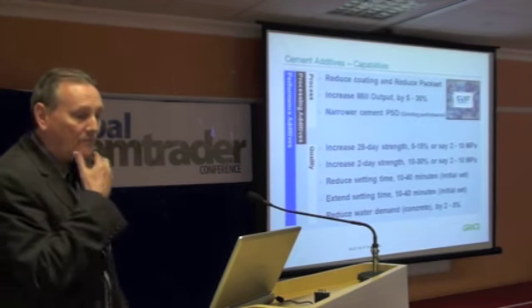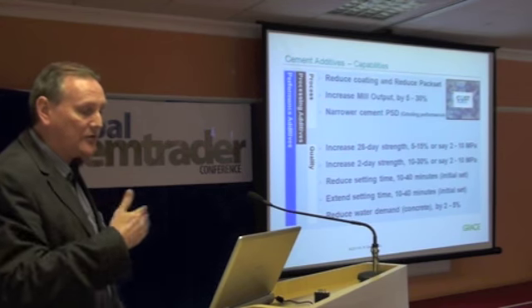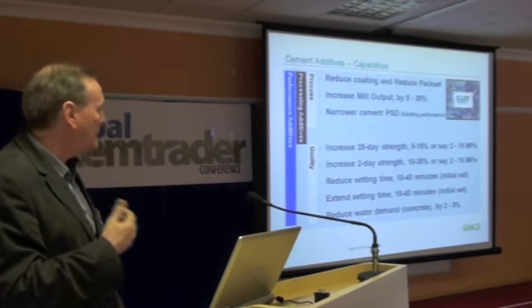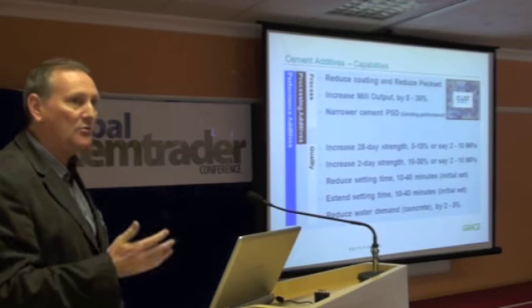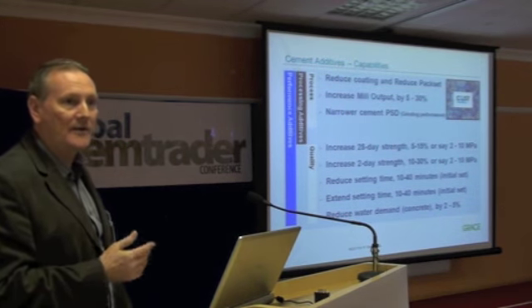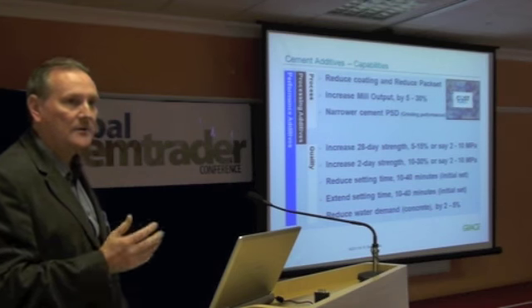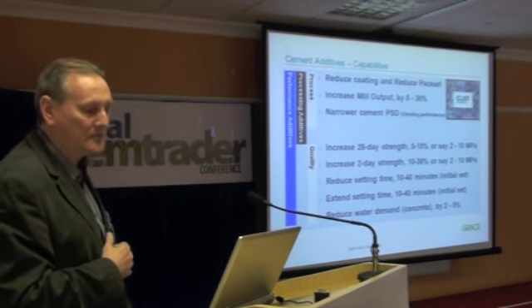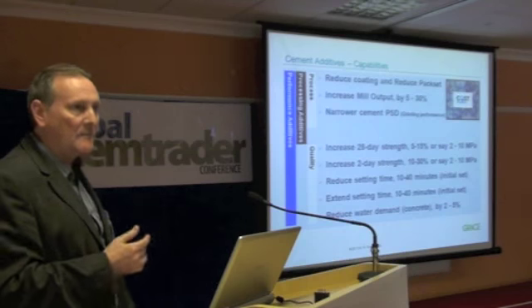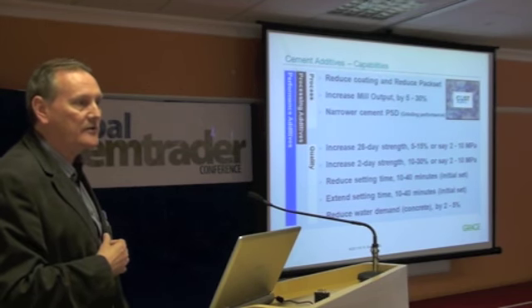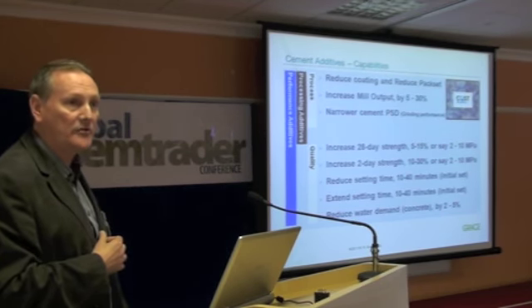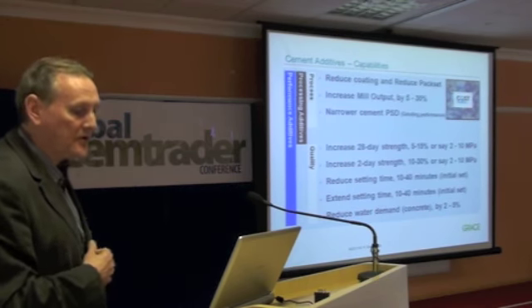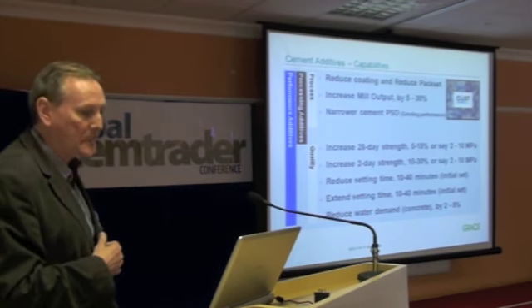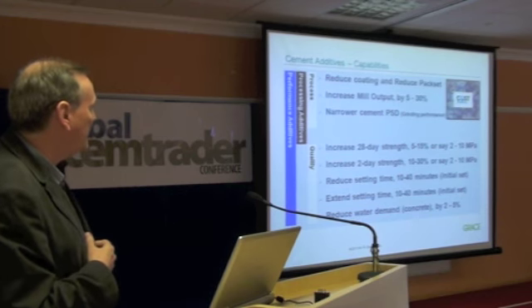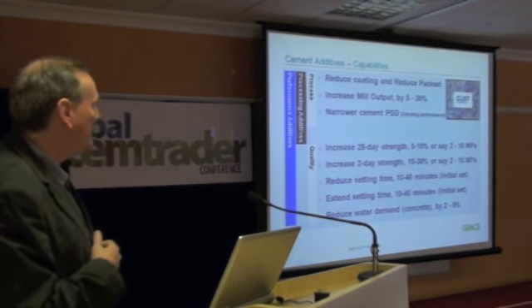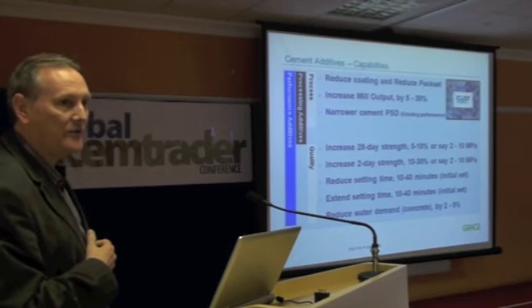So what can additives do? I just mentioned they reduce pack set, so they improve dry flowability. We normally talk about increasing the output of grinding units by anywhere from 5 to 30%. 10% is probably nearer the average. It gives some benefit in grinding efficiency. You end up with a narrower particle size distribution, which gives some performance changes, hopefully most of them beneficial. And we're talking about the chemical agents in number terms for strength, a 2 to 10 megapascal increase.